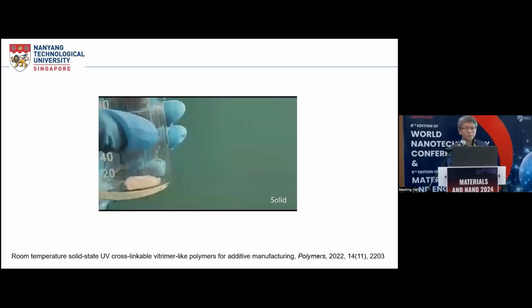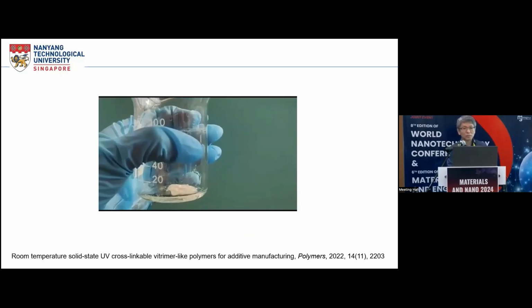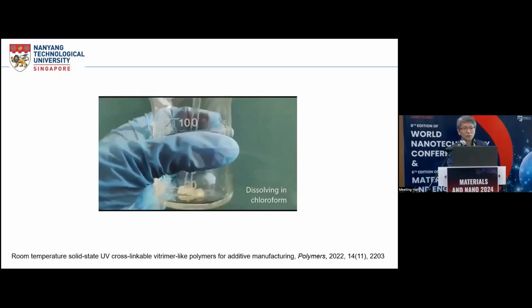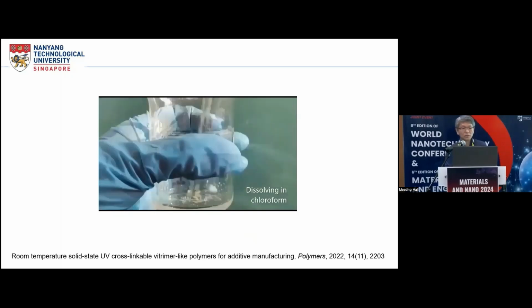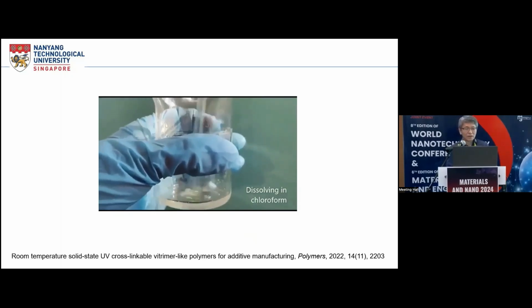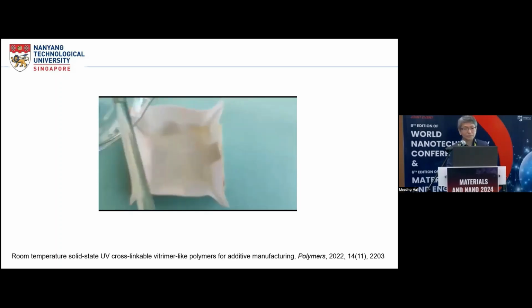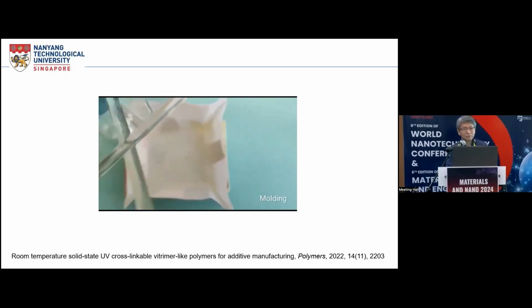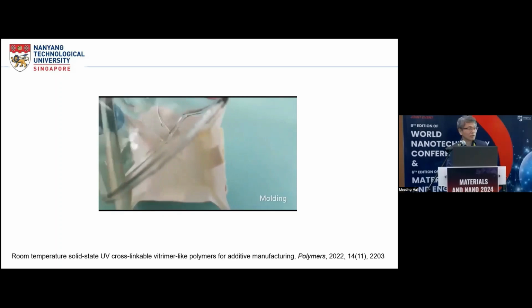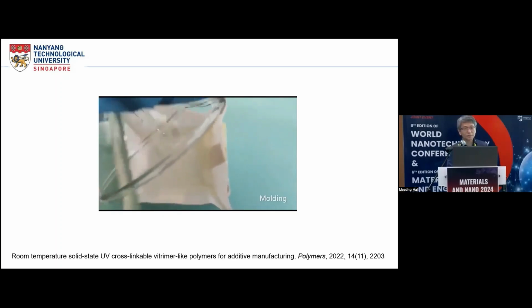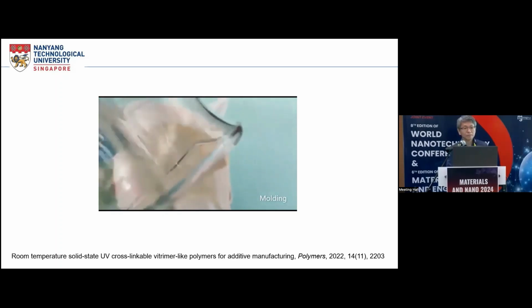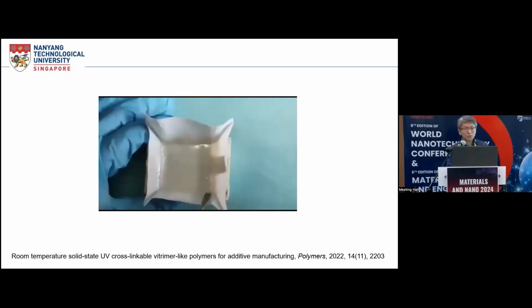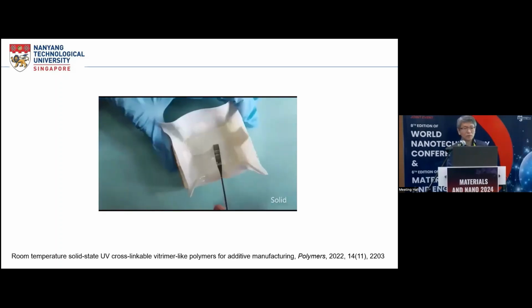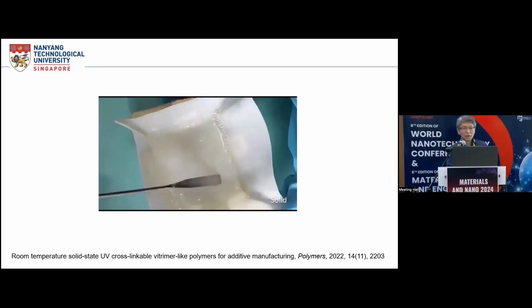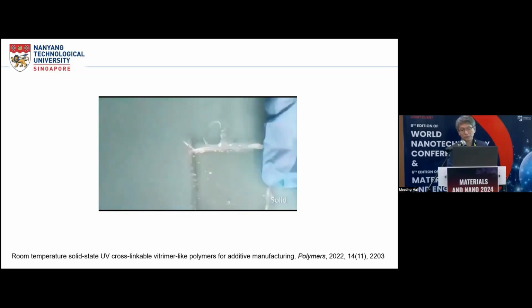Here we have a video to demonstrate this room temperature UV cross-linkable material. We dissolve the solid material in chloroform. Of course, we can heat it up to melt it, and then spread it on top of a container to get a film shape. After evaporation of chloroform, now we have a piece of transparent film.